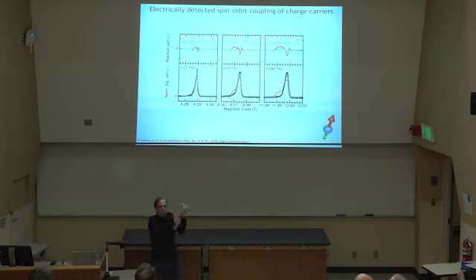And what comes out of this is experimental data compared to calculations, for different cases where we looked at ordered polymers in one way, and then polymers where the side groups were ordered in a different way, so in a completely anti-symmetric way and then a completely symmetric way. In reality, it's neither of these two, but it has to be somewhere in between. And then we also looked at which of these states that we calculated, the HOMO state and the LUMO state, corresponds to the two resonances that we assume here. So you get four different combinations reflected by red and blue and dashed and non-dashed respectively.